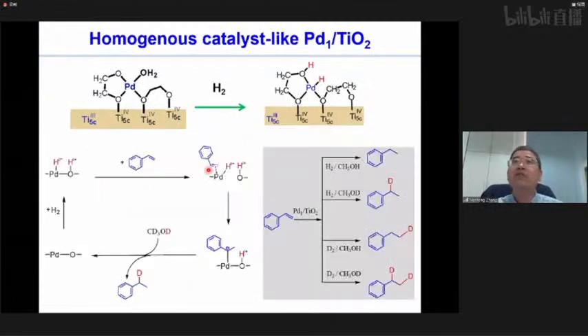And even for a really simple reaction, the hydrogenation of styrene, because we already know that the hydrogen can get activated into hydrides and proton, if we replace this H2 by D2, or the solvent by deuterated solvent, you can see we can get four products. Which means that with this understanding, it's possible for us to finally control their selectivity at the molecular level.